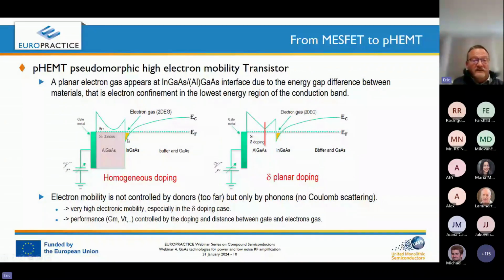which is that electrons are confined in the lowest energy region of this conduction band. So here you have a cut of the transistor, which is showing the gate of the transistor. Here, I would say the AlGaAs region where we have donors like silicon, and then here the channel, which is electron gas, two-dimensional electron gas. This case is with homogeneous doping. We have another trick, which is to replace the homogeneous doping by what we call delta doping.